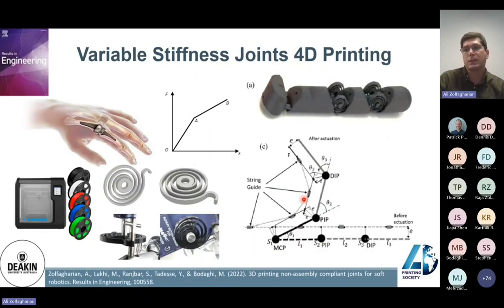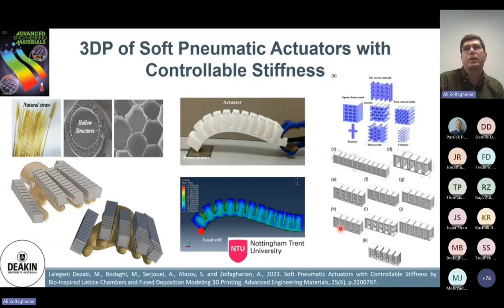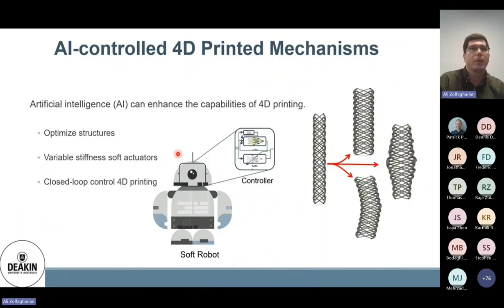Variable stiffness is another work that we are working on recently. With variable stiffness joints, we could change just the joints' material. You could see we could get different trajectories of the grippers or the muscles. And again, with our sister lab at Nottingham Trent, we could develop this sort of soft actuator using 3D printing parameters. We could harness different stiffness in order to make a trade-off between the bending and the force at our endpoint for pneumatic actuators.